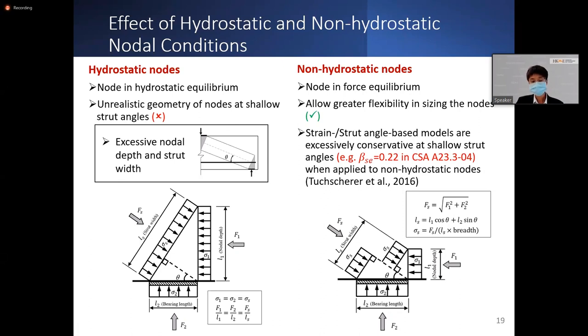On non-hydrostatic nodes, some researchers also point out that strain or strut angle based models may be too conservative at shallow strut angles. For example, here is the design strut efficiency factor 0.22 in the Canadian standards. This factor is rather small, so when it is applied to the realistic strut width here, the calculated force capacity may be too small, which is too conservative. So a similar strut angle based model is actually not recommended.